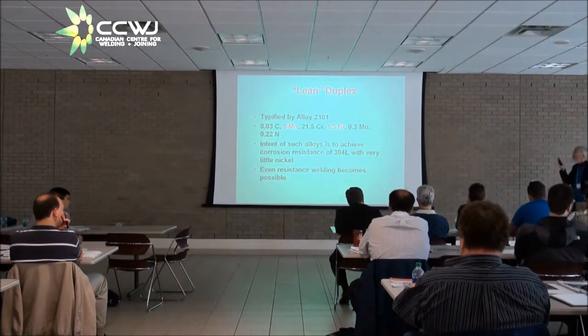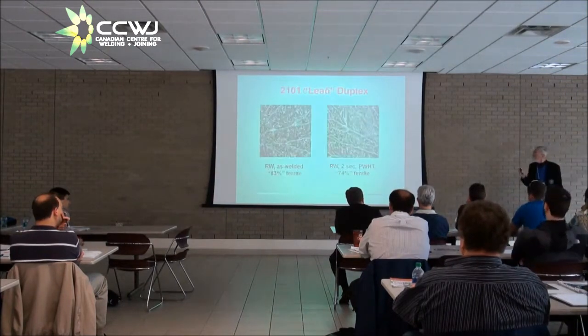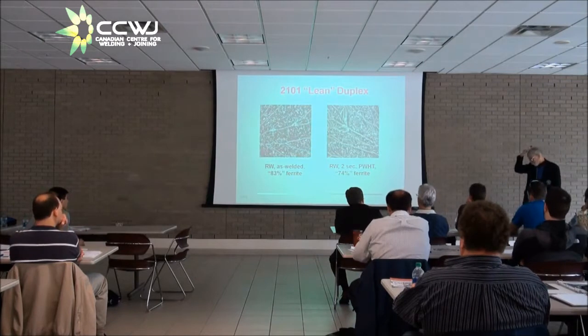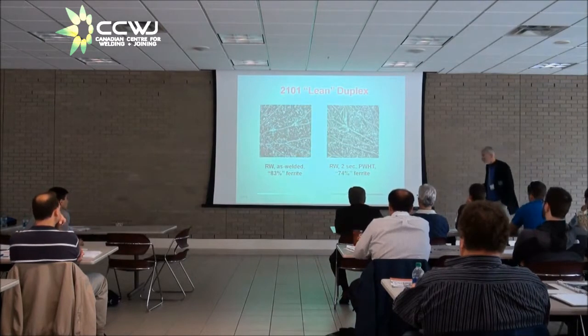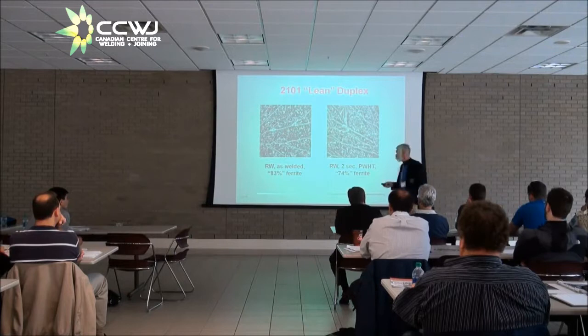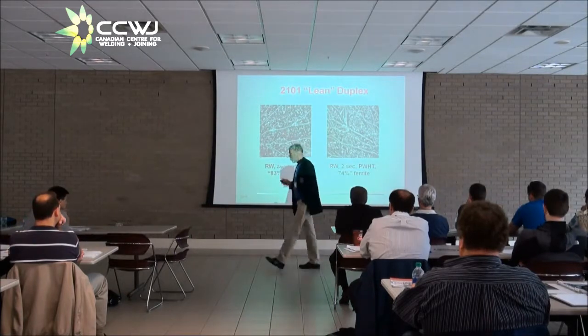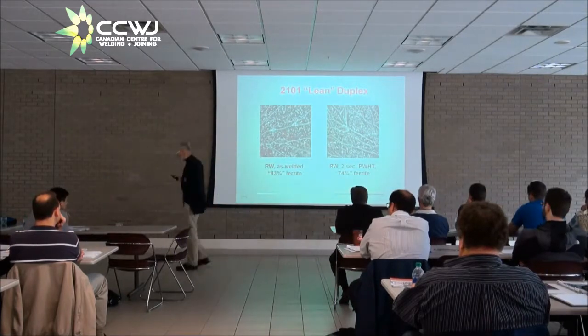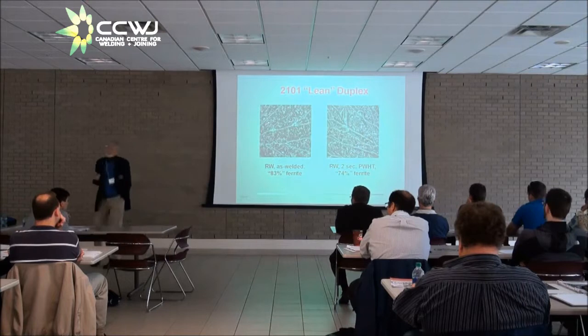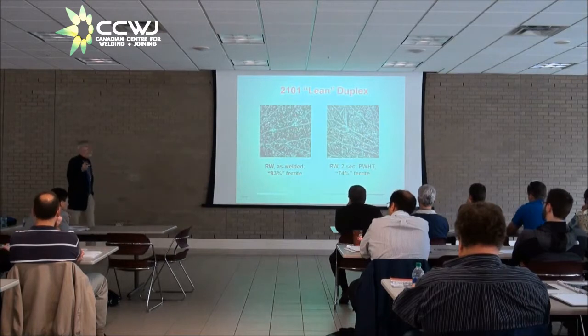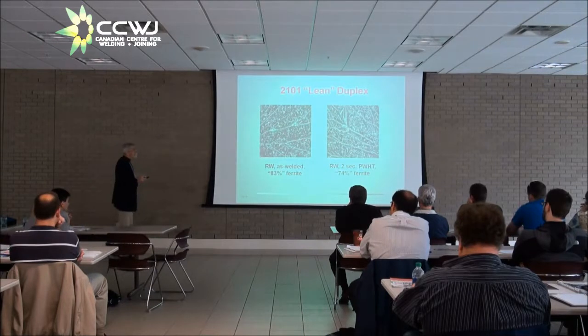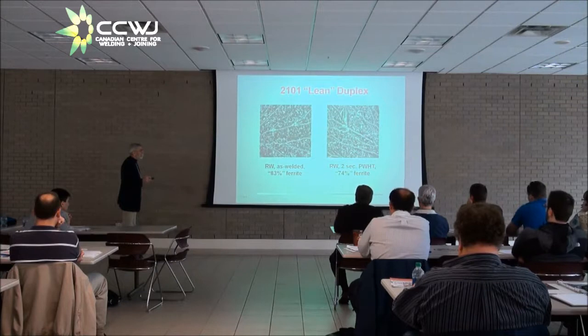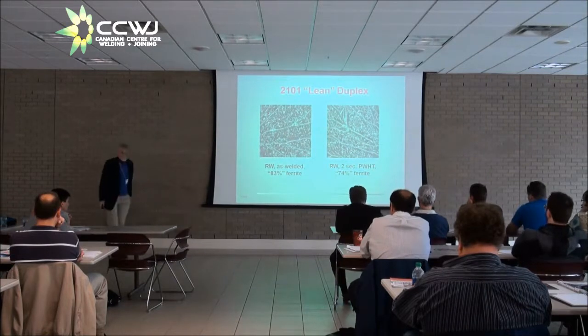However, 2101 is different. I'm indebted to Alan Weston for these four micrographs. We actually did some work on resistance welding of 2101, and you have to do some tricks with 2101 if you're going to resistance weld. The idea here again is to get some transformation to austenite. In the as-welded condition in a normal resistance weld, you get a little austenite on the grain boundaries and a little austenite inside and a lot of chromium nitrides.